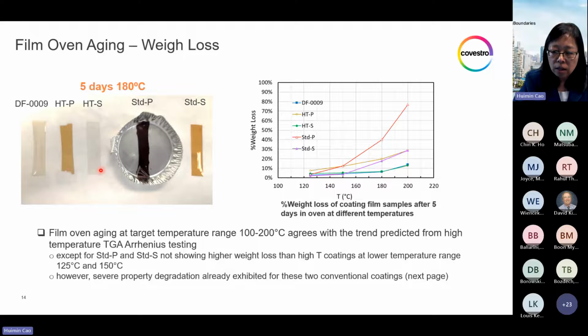And the HTS is not only a very nice film, but also non-yellowing at all, which is better than the single coat. And if you look at the weight loss from this oven testing, at the high temperature ranges, it shows clearly that the high temperature coatings are much better than the standard primary coating and secondary coating. But it's worthwhile to note that at low temperature range, such as 125, 150, the standard P and standard S did not appear to have a higher weight loss than the high temperature coating.